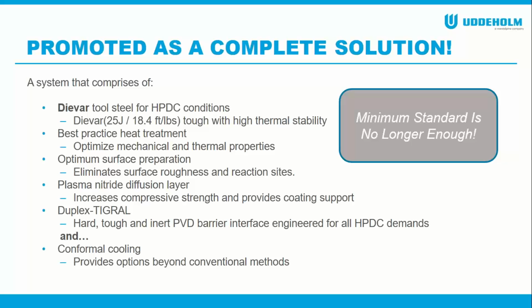So now you move on to surface preparation. This is very often overlooked and also left to a tool shop. Minimum standard for polishing for die casting is typically a 220 stone finish. For many molding areas, that is insufficient. So what we do is we review the tooling in each program, and we increase the level of surface finish for certain areas where we deem necessary. This will eliminate surface roughness, reaction sites, hanging up of the tooling during die opening and/or ejection.